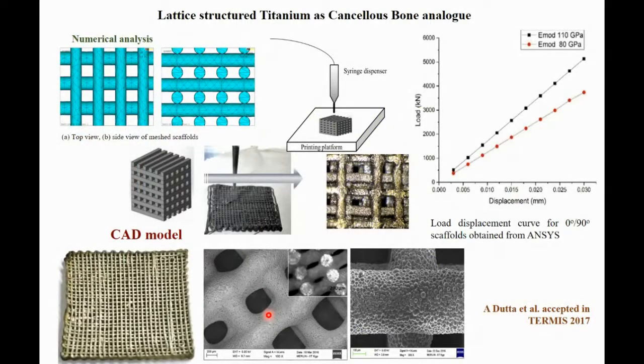Now I'm coming to the 3D printing of titanium. We have used a titanium-based slurry, and then it was printed using a printer. This printer was developed by us in the laboratory, and utilizing this printer, as you can see here, we made the 3D lattice structure. Here also we played with the lattice parameters, and we have seen that tentatively around 600 micron lattice or strand gap helps the maximum tissue ingrowth.